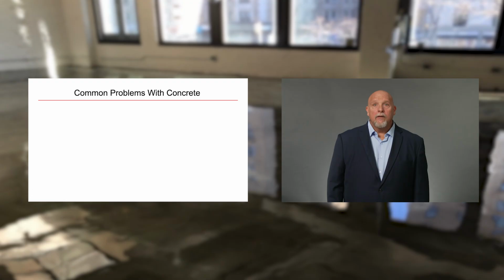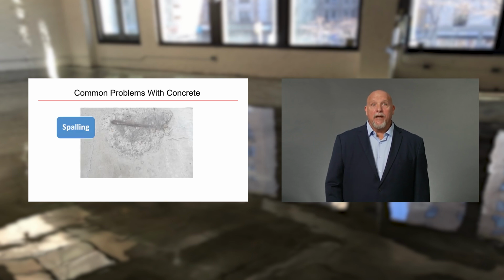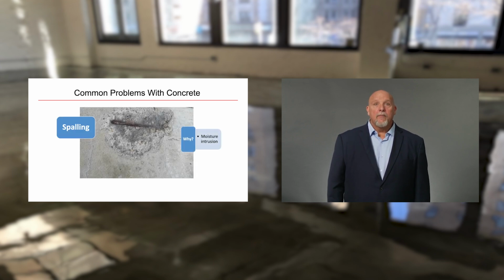As the embedded steel corrodes, it expands and generates sufficient tensile pressure to rupture the surface of the concrete. This type of surface delamination is also known as spalling. Since the main cause of spalling is moisture, the application of a protective coating will help prevent the premature failure of the slab. Spalling is similar to scaling, except the expansion occurs from deeper within the concrete, causing the surface to disintegrate into larger fragments.